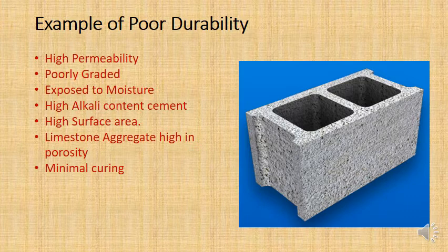It's also often exposed to moisture. These blocks are used for walls where it rains on them. And even if you do paint it, often the paint is not maintained, and so water gets in behind the paint. It uses a limestone aggregate. So one of those things is the limestone aggregate has a very high porosity. So those aggregates can get water into the aggregate particle itself and expand the aggregate particle. That breaks down the concrete.